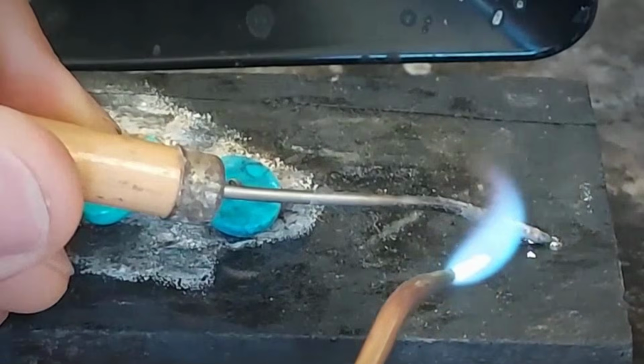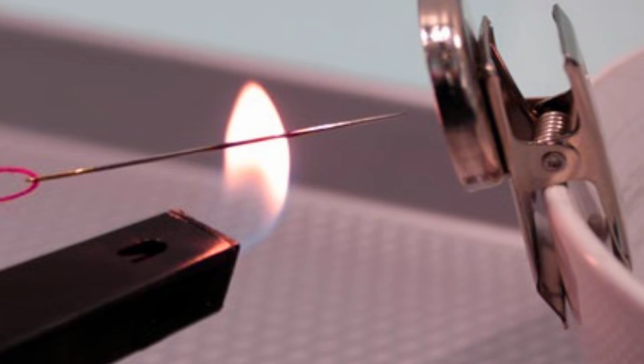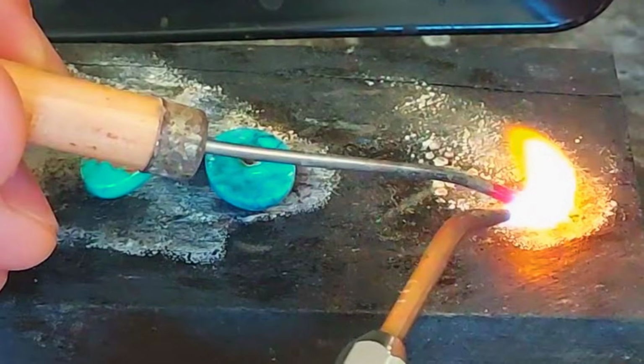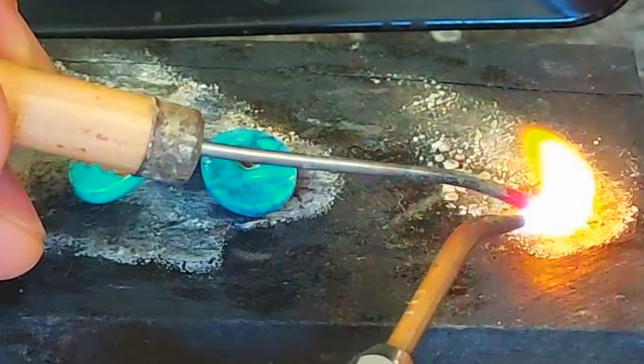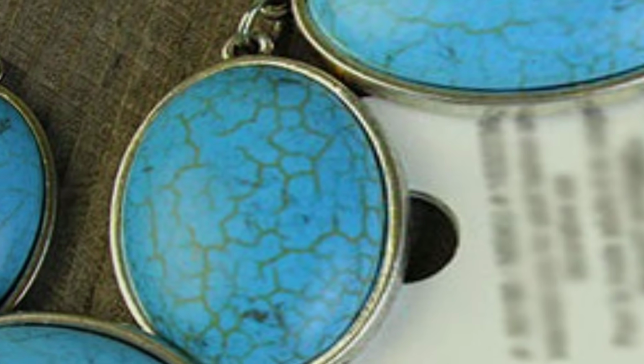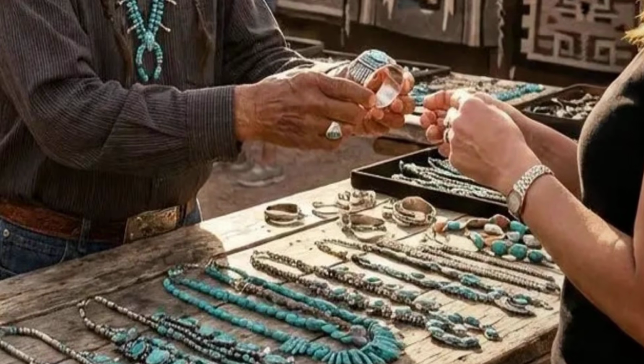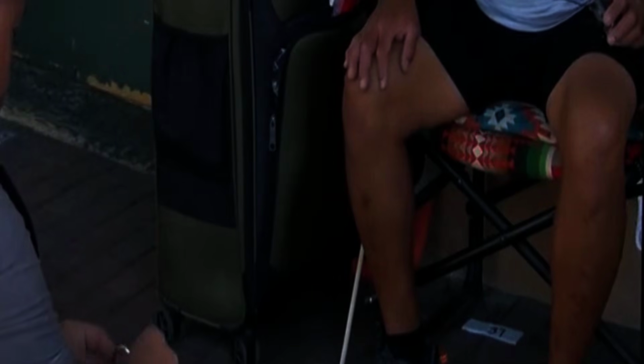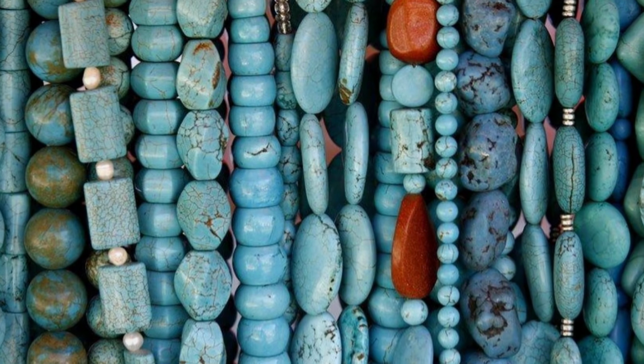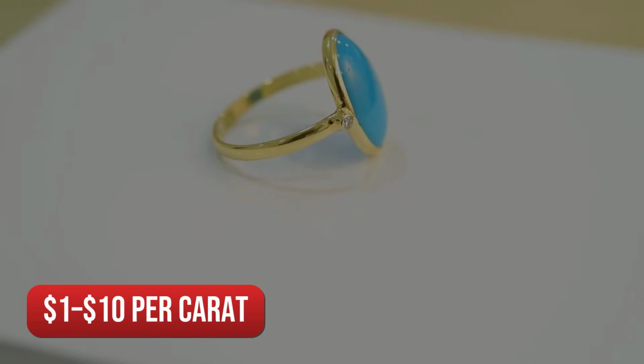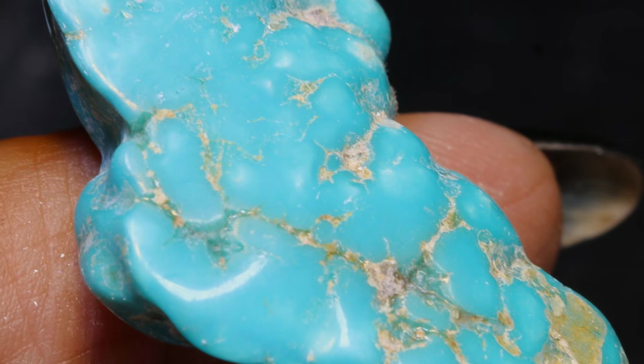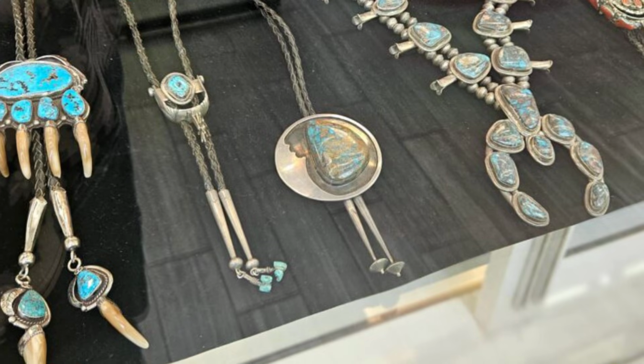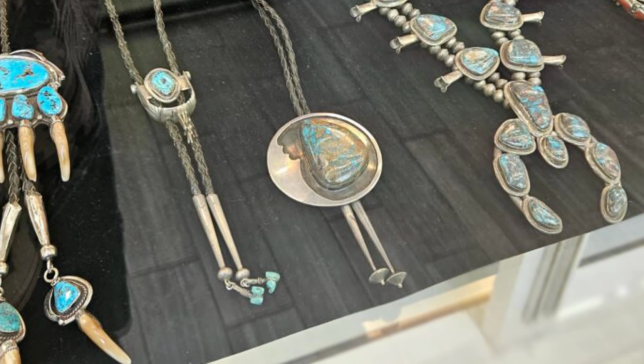The hot needle test is the giveaway. Heat a sewing needle with a lighter and touch an inconspicuous spot. If you smell burning plastic or see the surface soften, it is reconstituted. This fraud is rampant in the American Southwest, especially in Native American artisan markets where buyers trust the cultural provenance. Retail for reconstituted, $1 to $10 per carat. Natural high-grade turquoise, $100 to $1,000 or more.